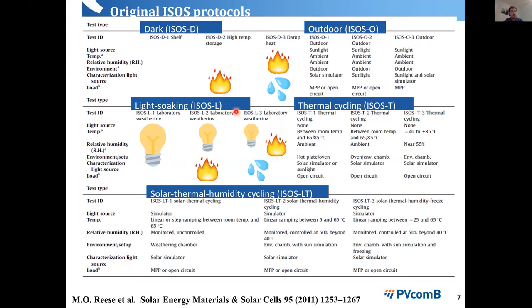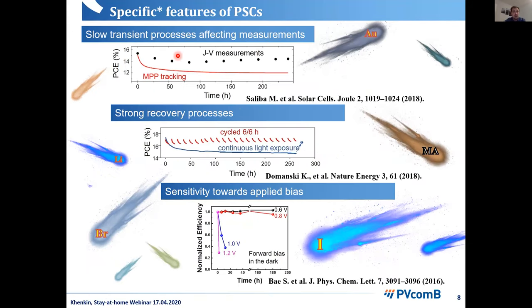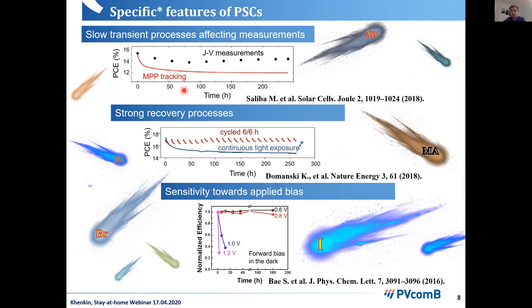The same logic was used when introducing new protocols specific to perovskite PV. Perovskite devices are known to have slow transient processes and history on the JV measurement, so the measurement procedure needs to be updated. In this context, MPP tracking has become more and more important, and if you want to certify a cell, five minutes of MPP tracking will be required. For stability measurements we rely more and more on MPP, not only for efficiency traces but also because MPP is the most natural biasing condition.